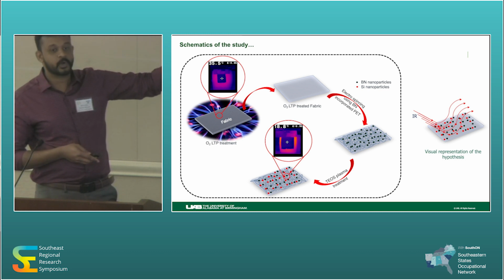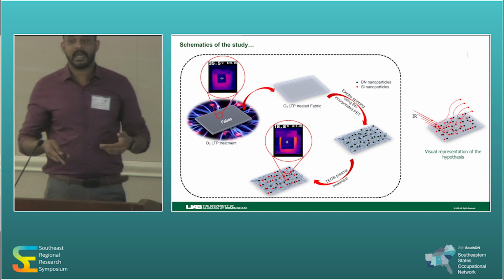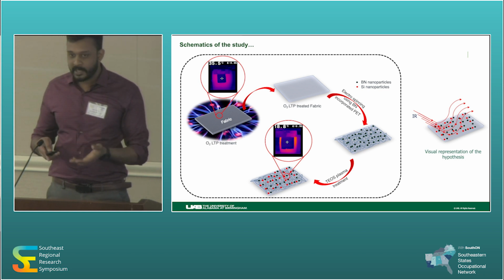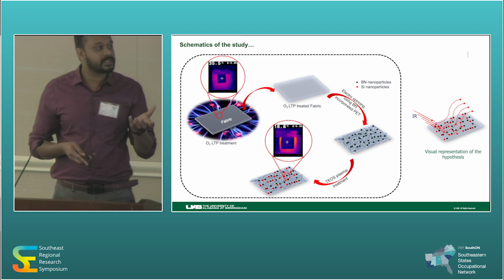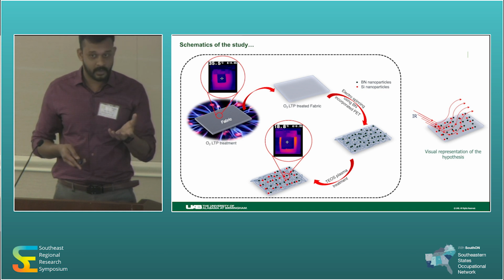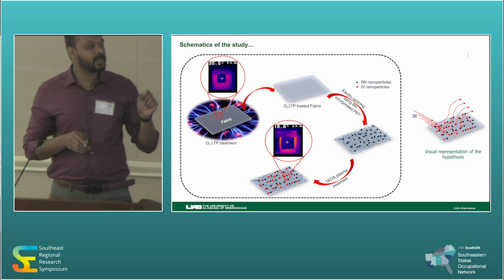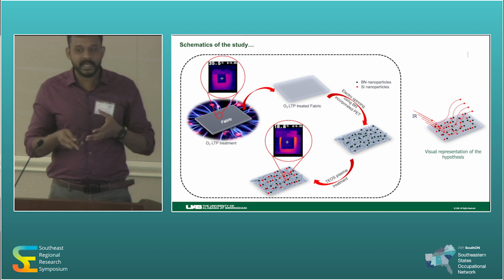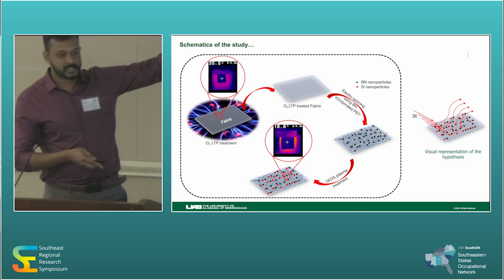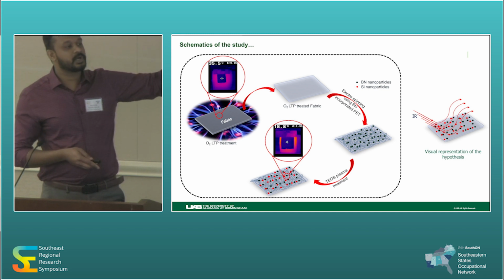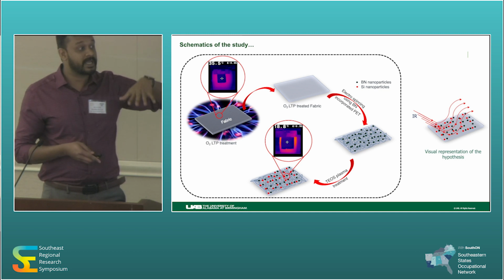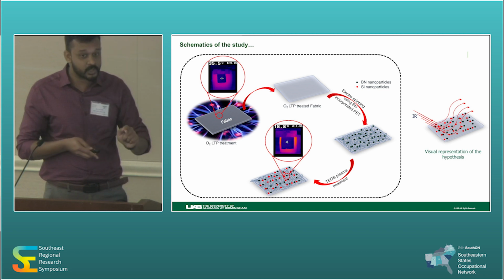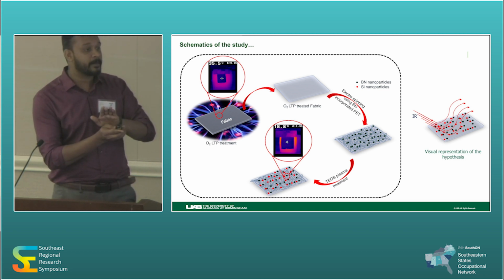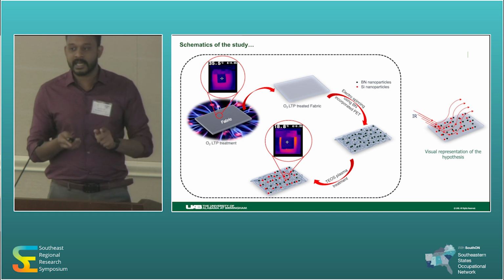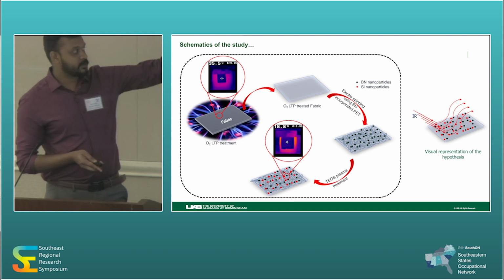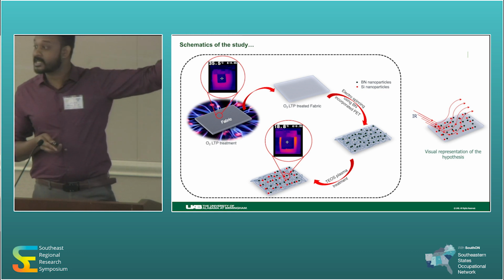Then after that, we performed oxygen plasma treatment. Actually, we are using a low temperature plasma treatment. That means inside the plasma chamber, the temperature will be a maximum of 35 degrees or sometimes less. So it's a gentle plasma that doesn't do any harm to the fabric. Oxygen plasma is basically for surface etching, that means creating surface roughness to make sure the next coating adheres properly. That's why I mentioned stable coating. So oxygen plasma is for surface etching or surface activation.